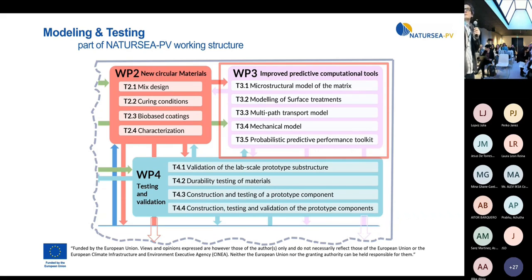In this work package we have 5 different levels. Actually, we follow a multi-scale approach. First we do the binder, that is, the microstructure of the binder matrix. We use thermodynamic modeling to predict the phase assemblage and the hydration, and how the pore structure develops. Then we have the modeling of the surface treatments. Then we have a mesoscale model, which I will show later, where we explicitly include the aggregates and the interfacial transition zone.